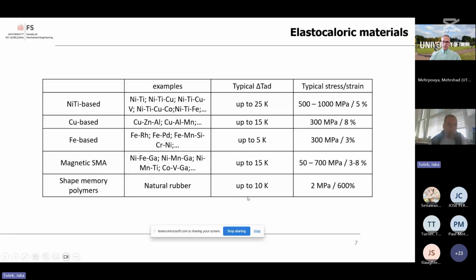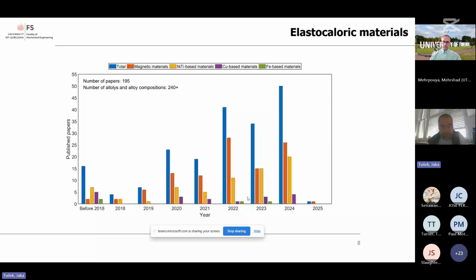The development of new improved elastocaloric materials has been a very hot topic in the last couple of years, as shown in this plot, which shows published papers per year over the last 6 or 7 years, and we can see that a great majority of the papers were produced in the last 5 years. It should be noted that nowadays elastocaloric materials, mainly binary nickel titanium alloy, have not been developed for elastocalorics, but for other applications such as actuators or biomedical applications. So it's not optimized for elastocalorics. So there is significant room for improvement in the development of elastocaloric materials.